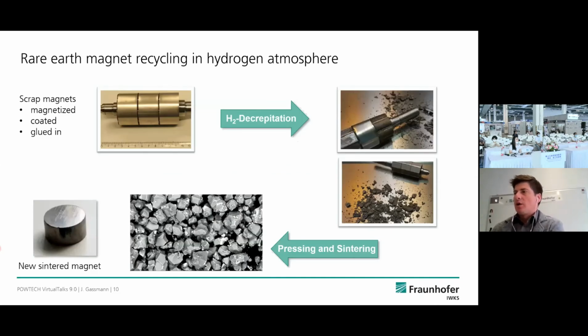Additionally to that, one can also use this process for separating magnetic materials from non-magnetic materials. Like in this case, it's shown by a rotor where permanent magnets are located under these metal plates. After hydrogen decrepitation, one can see the rotor is totally unaffected by the hydrogen process. However, the magnet is powderized and can be separated by sieving. Afterwards, the powder is processed into magnets like I showed before.